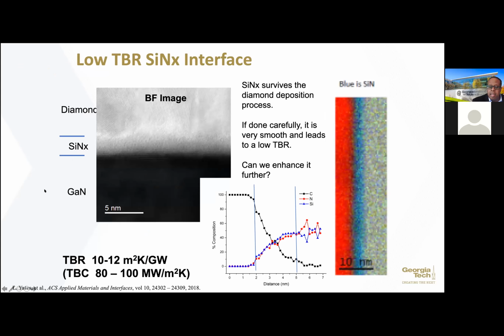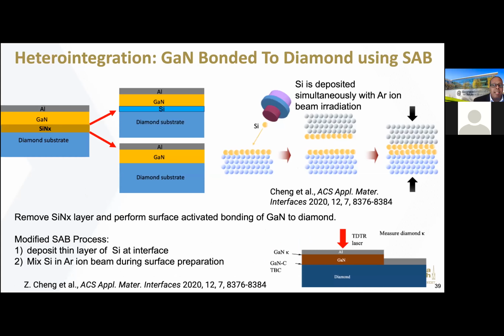It's very thin. And this leads to some of the lowest thermal boundary resistances that we've ever seen between GaN on diamond. And so thermal boundary resistances on the order of 10 to 12 meters squared K per gigawatt, or in terms of conductances between 80 to 100 megawatts per meter squared K. And so I want you to keep that in mind, this number right here between 80 to 100, as we go to, obviously, how would you bond these? That's the other step. Can we do it the other way?